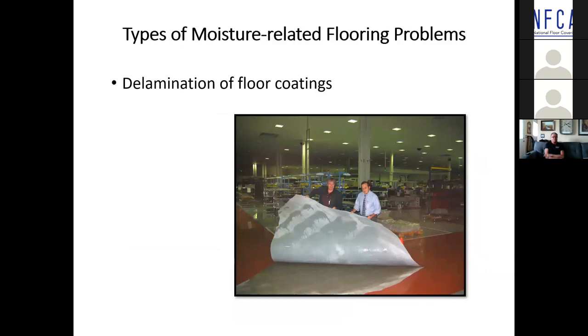Delamination of floor coatings. This shot here was the facility that first produced scanners for the airports after 9/11. It was a former Lucent technology facility. They tested, and the moisture levels were unacceptable. They bought into putting down a 2-part epoxy moisture mitigation system. They started shot blasting the floor, 200,000 square feet. So they were shot blasting 15,000 feet, move over to another 15,000, another 15,000, another 15,000.